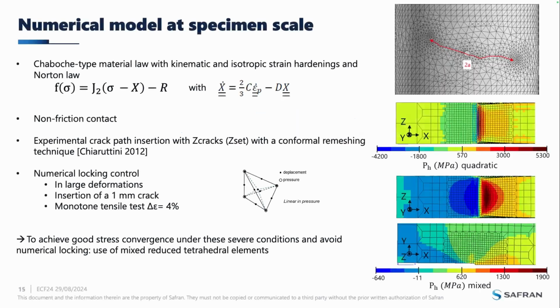So first, I set up a model at the specimen scale. I use a Chaboche type material with one kinematic and one isotropic strain hardening and a Norton law. First, I implemented frictionless contacts, and here you have a zoom of an example of an experimental crack path insertion with Zcracks with a conformal remeshing technique. And because of the intense loading, numerical locking can occur.